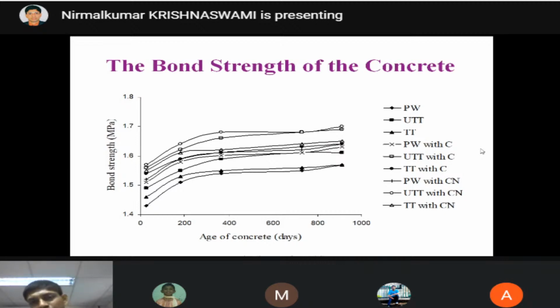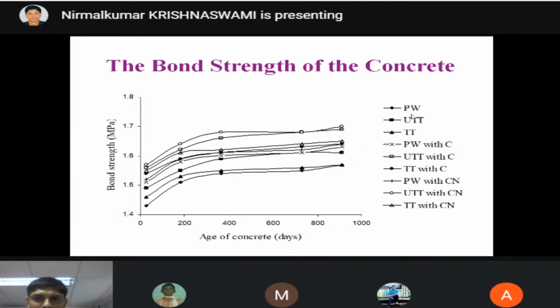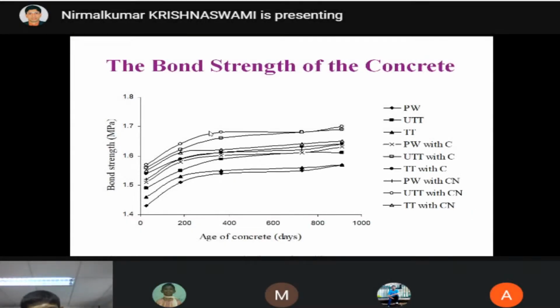Then comes the bond strength of our concrete. Bond strength, I hope you know, we insert a rod in the concrete and pull it out and determine the strength. So here the bond strength I received is a minimum of 1.4 Newton per mm square and a maximum of 1.7 Newton per mm square, and this is our benchmark. So the benchmark is around 1.7. Even with the addition of admixtures, there is no much effect. It varies from 1.4 to 1.7, so it's a good sign that the bond strength of the concrete is good.